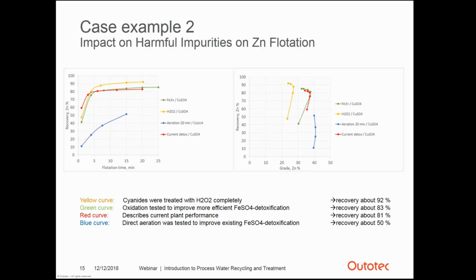The green curve presents the flotation results after water treatment with ferric sulfate, and we can see that also that method gave relatively good results in flotation, with the recovery being 83% and grade 32. Aeration of the process water before the current detoxification seemed to improve zinc flotation only slightly, as you can see in the blue curve, having a recovery of about 50%.